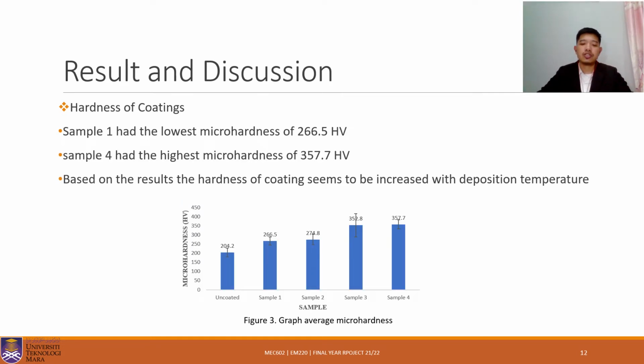According to figure 3, sample number 1 had the lowest micro hardness of 266.5 Hv, while sample number 4 had the highest micro hardness of 357.7 Hv. Based on the result, the hardness of coating seems to increase with deposition temperature.